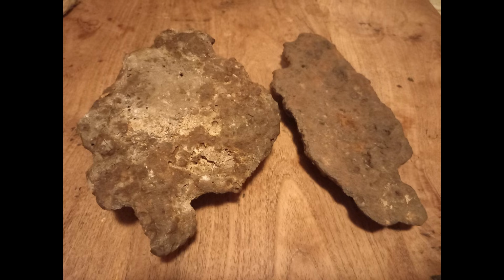So let's also see if we can find evidence of local high carbon steel technology in the Netherlands. And luckily there is. At the iron production site at Heeten, already in the late Roman era, hypereutectoid high carbon steel artifacts were being produced, as is evident from the famous Heeten artifact, which shows a 2% carbon content and furthermore was already heat treated and back tempered, showing that high carbon steel technology was already available in the Netherlands from quite early periods onwards.